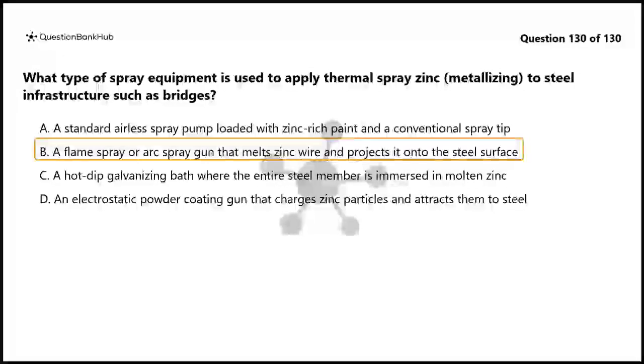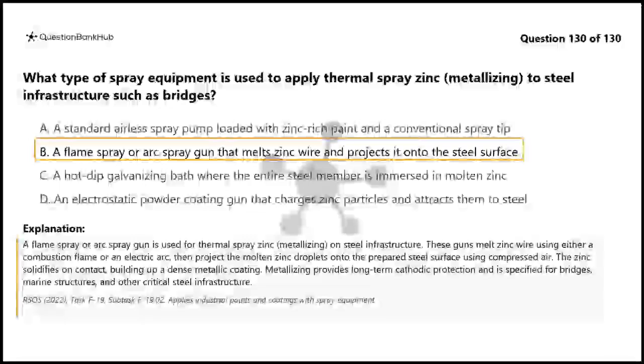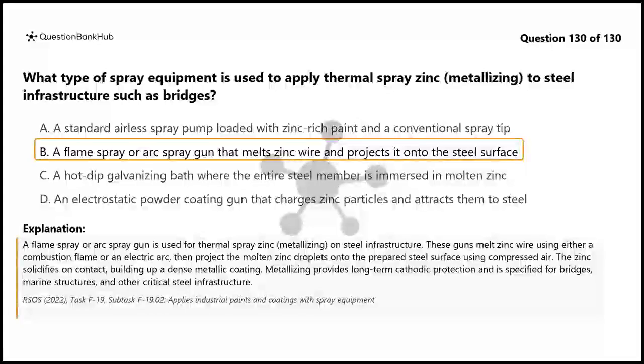The correct answer is B. A flame spray or arc spray gun is used for thermal spray zinc, metallizing, on steel infrastructure. These guns melt zinc wire using either a combustion flame or an electric arc, then project the molten zinc droplets onto the prepared steel surface using compressed air. The zinc solidifies on contact, building up a dense metallic coating. Metallizing provides long-term cathodic protection and is specified for bridges, marine structures, and other critical steel infrastructure.